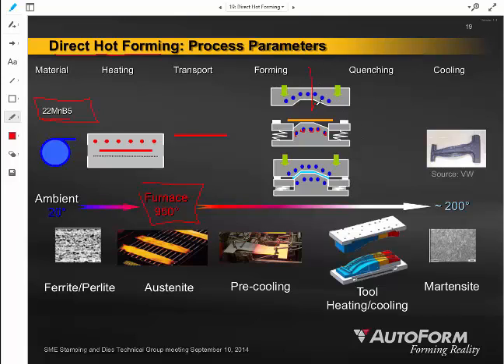And that way, when we close the die, the material is getting deformed, and the material is quenching in the meantime. So normally what will happen is you put the blank in, it takes 1 second, maybe 1.5 seconds to close the die, and then the die is going to stay closed, maybe dwelling at the bottom for, I don't know, 3, 5, maybe even 6 seconds, cooling and quenching at the bottom of the stroke. And as that's happening, the material's microstructure is going from this 950 degree austenitic microstructure possibly towards martensite or bainite or ferrite microstructure, and achieving certain yield strength and tensile strength characteristics.